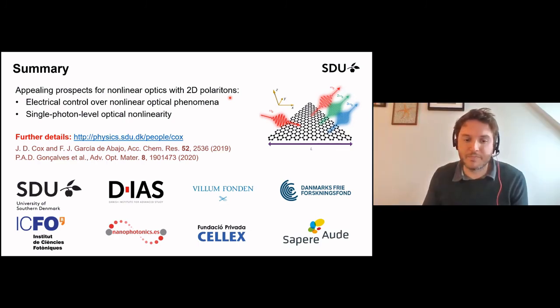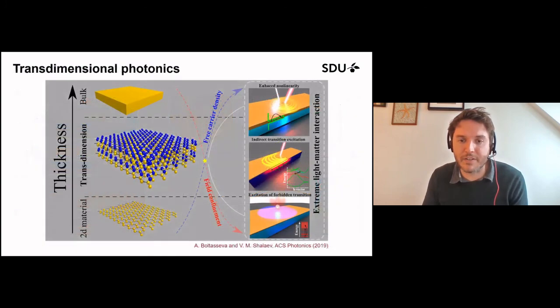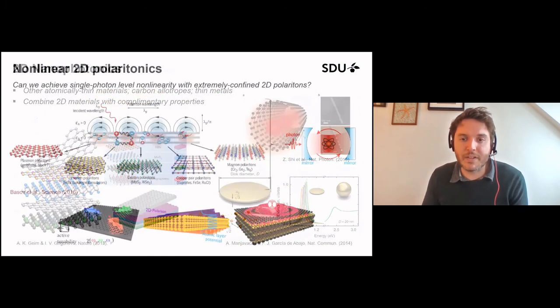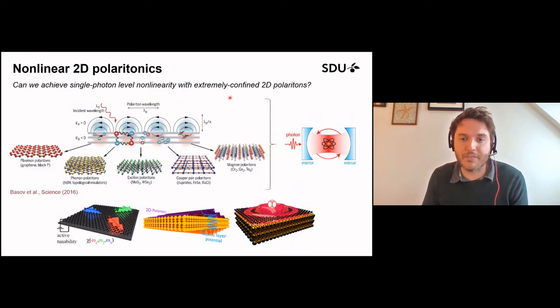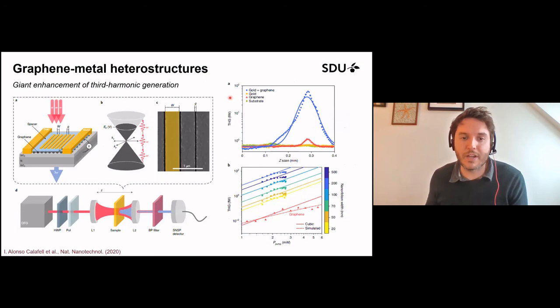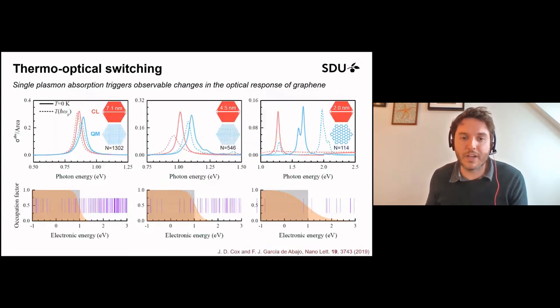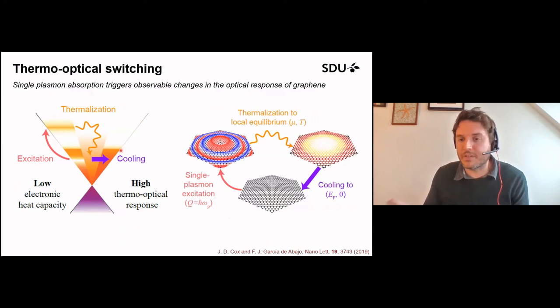The main advantages here, like with the plasmons in graphene, like having a truly 2D system really does enhance the confinement. And a lot of the physics I've been discussing is coming out of the fact that you have linearized dispersion, so you dramatically change the thermal distribution of electrons. These kinds of phenomena are really appealing, but definitely doping semiconductors can also give you this kind of 2D electron gas. But it's a give and take. Depending on your application, you may want to use one or the other.